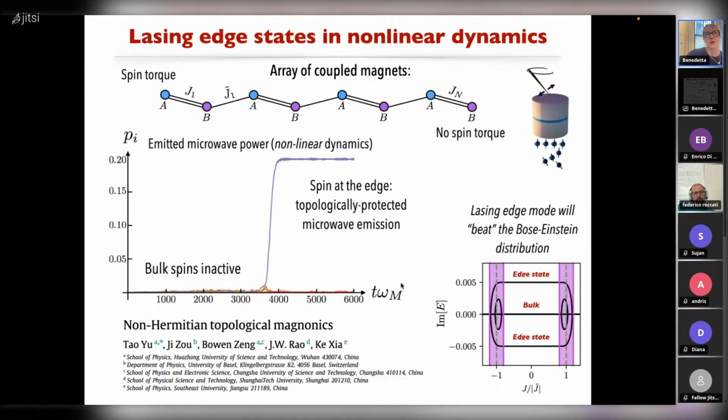I could think about it. I would say it will depend on a lot of parameters, in the sense that if my J1 is ferromagnetic, which was the case in our model, and I'm simulating this one driven, this one not, the other one driven, and really driven very far from equilibrium, then J1 is going to try to keep them aligned, so it's going to fight against the spins misaligning and starting lasing.